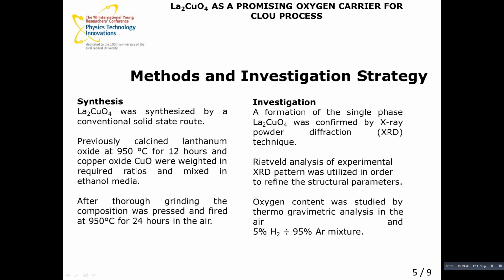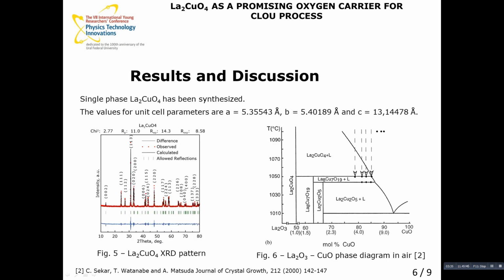Polythermal dependences were recorded consecutively in air and in an atmosphere containing 5% of hydrogen in argon. There are several lanthanum cuprates presented in Figure 6 which exist in air. Experimentally, the X-ray spectrum for the synthesized oxide is shown in Figure 5. According to the results of Rietveld analysis, lanthanum cuprate is crystallized in orthorhombic symmetry with the Cmce space group. The values of unit cell parameters supplied within Figure 5 are in good agreement with literature data.